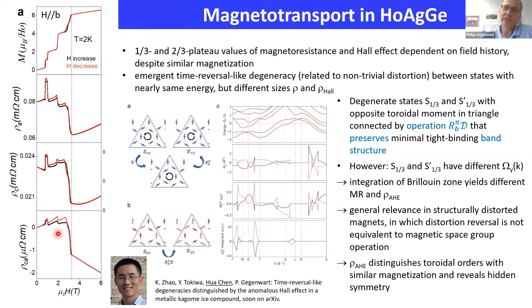So the general relevance of that is that in such structurally distorted magnets, where the distortion reversal is not equivalent to a magnetic space group operation, we can use the anomalous Hall effect to distinguish these different states, which here have opposite orders, which have a similar magnetization, and we can reveal this hidden symmetry by the magnetotransport data.